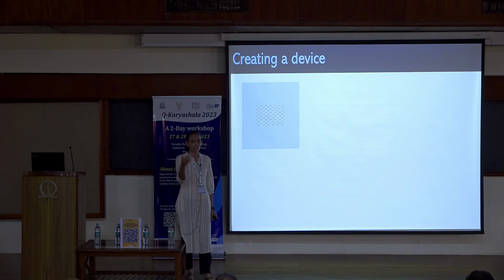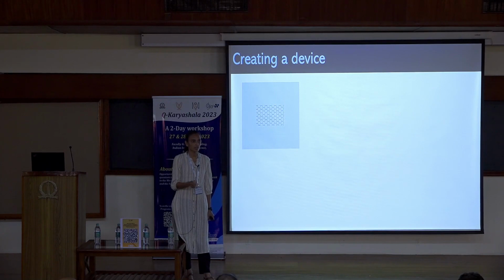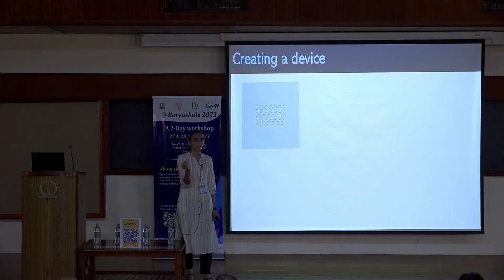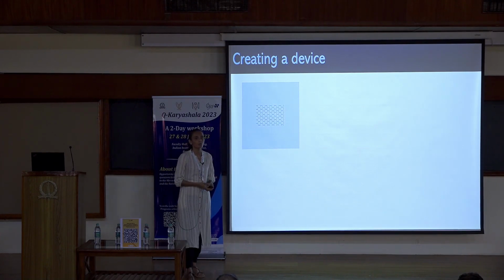But you can use filters to enhance the contrast. Sometimes people have even written codes to figure out if the contrast matches a single layer or bilayer. So that's how, when you do it, you figure out. Most of the time, if you're good at that process, right? I said it in simple terms, but there's a particular way in which you have to transfer the tape onto the wafer. If you get good at it, then you will not have those bulk graphite, but rather the chances of getting graphene are more. It's like an experimental optimization.